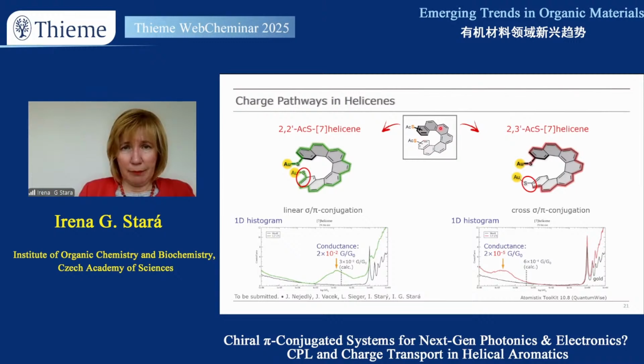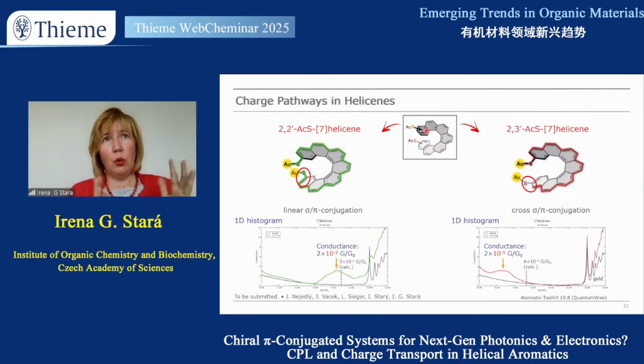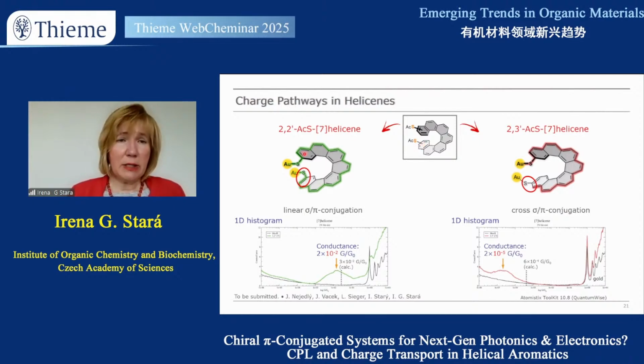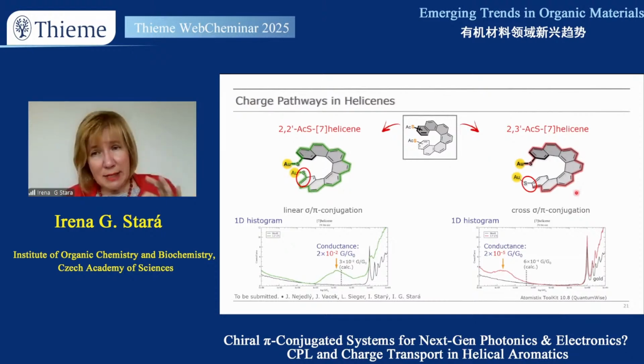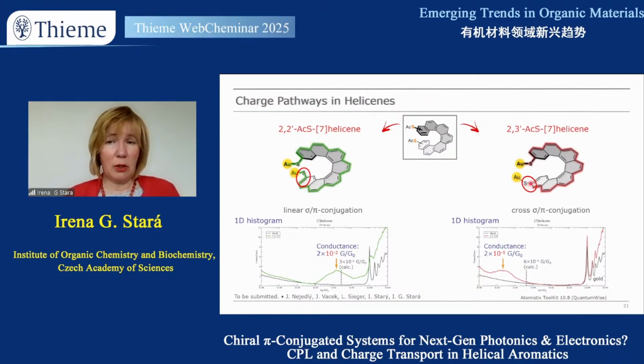We decided to employ heptahelicene because in heptahelicene it's possible to have internal stacking of these rings, which means it allows an alternative channel through the space. And it is shown in this picture. Here you can see it is a good communication between these electrodes. It's of course a simplified model, whereas in this structure the communication is a bit worse. So this is a linear pi-conjugated molecule, and this is called the cross-conjugated molecule. And we measured the conductance, and you can see here there is a 3 orders of magnitude difference. Higher is in the linearly conjugated molecule.